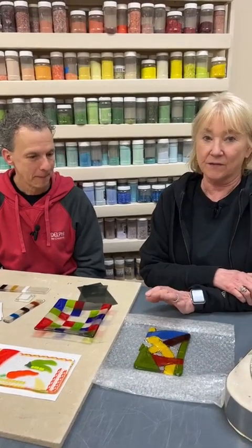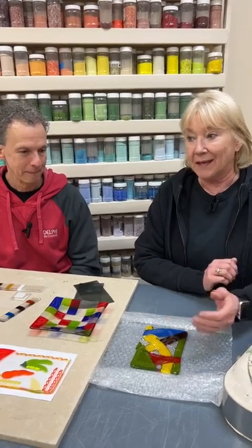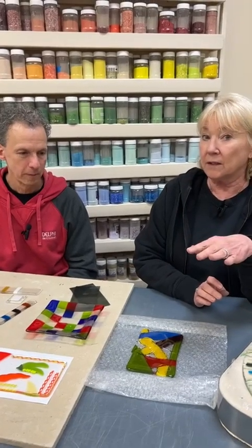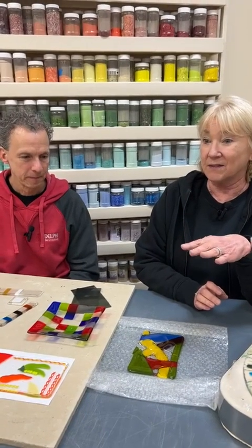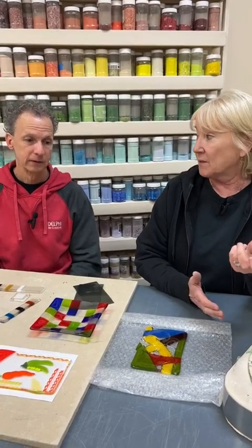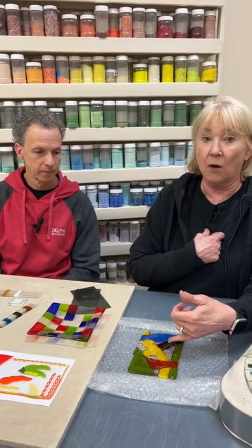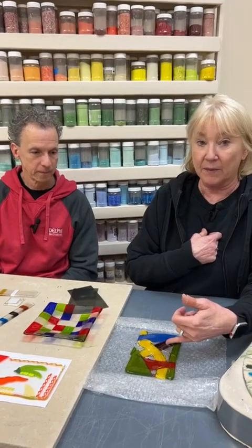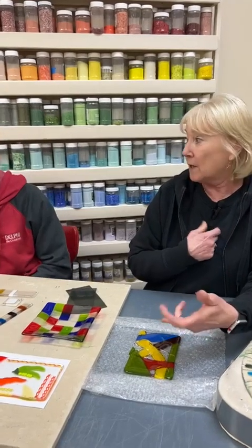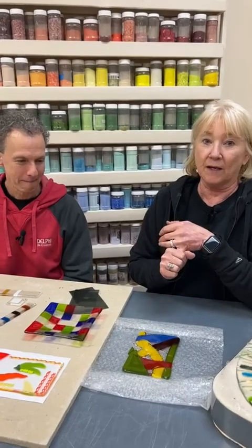I mean, that's not what this video is about, but when you have this kind of meandering, following cracking, you really do want to look at it closely, because it's often because you've got something in there that wasn't compatible with the rest. So in this case, if this were me at home, I'd be looking for the rest of that yellow. You know what I mean? Get it out of your stock, so it can be helpful in the fact that you're not going to use it again.